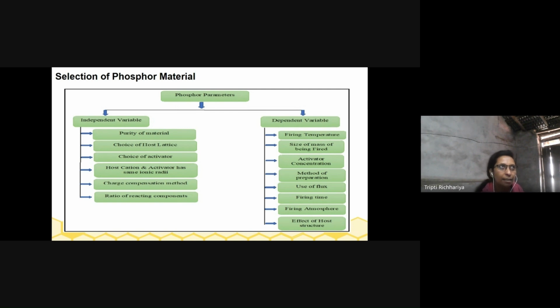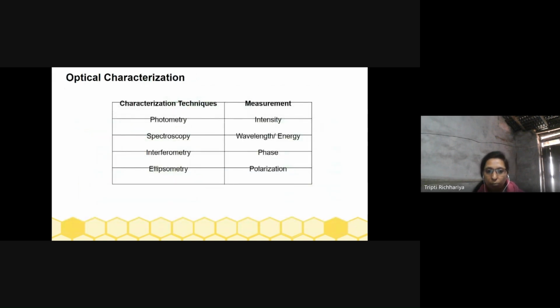If the time is greater, the material will not be properly synthesized. If the temperature is greater, the material will not be properly synthesized. That means a particular time and temperature is needed. Such parameters are known as dependent parameters, because they depend on each other. These parameters should always be kept in mind while preparing the phosphors. Now, based on the application point of view, various types of characterization techniques are used. In this talk, we are basically focused on the application of display devices as well as smart agriculture and fingerprint detection. So here we have to discuss the spectroscopic techniques that generally measure the wavelength or the energy.